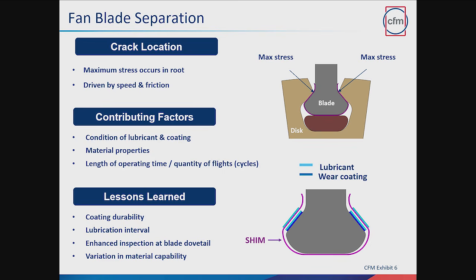So from a cause perspective, root cause, why did the blades crack? That contact pressure I was talking about occurs when the blade loads out at speed. Centrifugal load wants to load out against the disc, and it creates a big contact load between the two surfaces. The friction level will determine that stress. The two surfaces are sliding slightly relative to each other. The higher the friction, the higher the stress. And that's really a key contributor to understanding the cracking seen in the fleet.